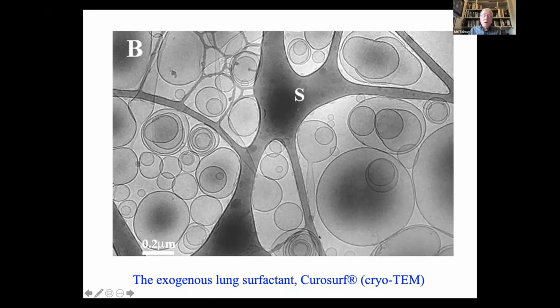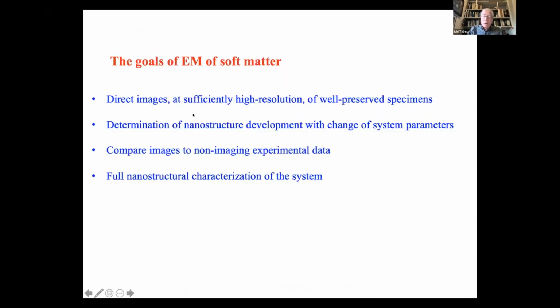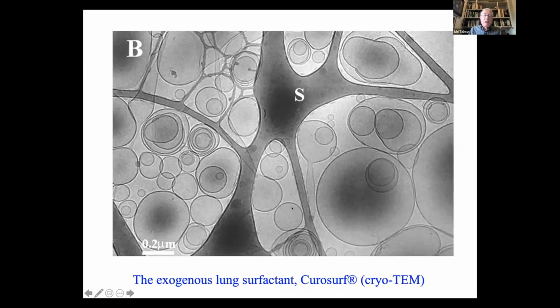and this is not really a natural lung surfactant, but this is artificial lung surfactant that is used in treatment of premature babies. But you see here too, we can tell very clearly that we have single layers and multi-layered and concentric, your Chinese boxes and your Russian dolls, everything is seen here quite easily. S here designates a support film, and basically what we see here is the vitrified water. I'll talk about this in a minute, and our particles in it. So what we have here is water that is not crystalline, but is really glass-like. And this is really very important, as I will say in a minute.